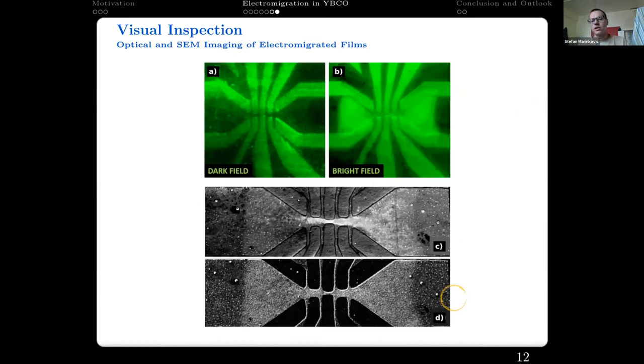As I mentioned, on the resistance versus temperature curves, we suspect inhomogeneous growth. So we have taken a look under a scanning electron microscope, as you can see in image C, and we see indications of filamentary growth throughout the material, with a higher brightness, higher signal intensity coming from these filamentary growths. But this image is from the InLens sensor, which collects all the secondary electrons, while this one collects only the lower energy secondary electrons. This is an Everhart-Thornley detector, and it indicates more of a topological contrast. And we see that there is not much difference in the topology, but there is this filamentary character that we see here.